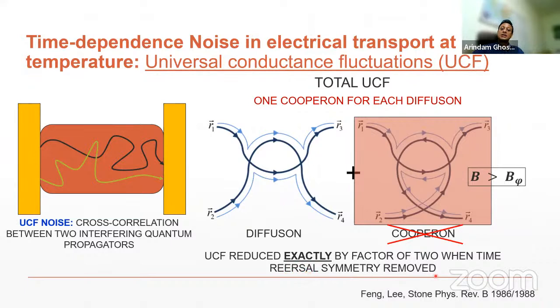And this is called time reversal symmetry, right? Because we are removing the phase, we are adding random phase so that the path which is going forward and the path which is coming back have now accumulated different phase. Okay. Now this exact reduction of noise by a factor of two is our experimental probe. And not only when applied magnetic field, but also if there is magnetic structure or magnetism present in the system, we will have this part removed spontaneously.